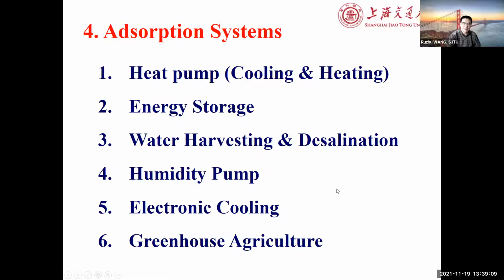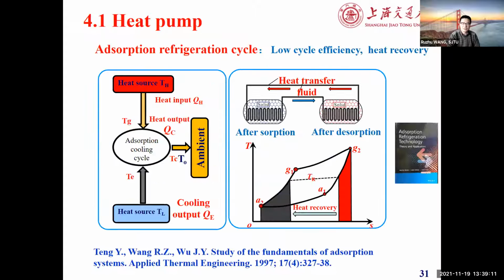So with this system, we could develop a variety of adsorption systems. This just shows that for heat pump applications, usually we need 2 adsorbers to get continuous operation, just to shift the phase of both adsorbers. So in this case, we could introduce heat transfer fluid for the heat recovery when one finishes generation, while the other finishes adsorption. So the high temperature from the generation could be used to regenerate the other adsorber. So you need the heat transfer fluid for the heat recovery.